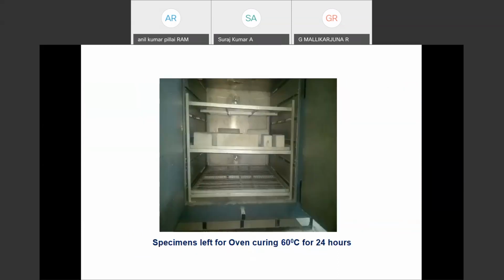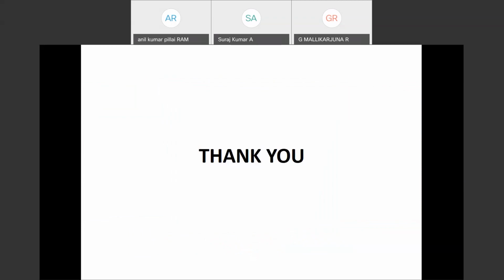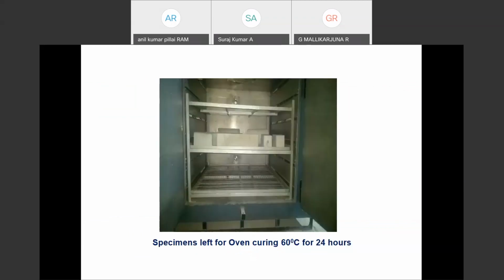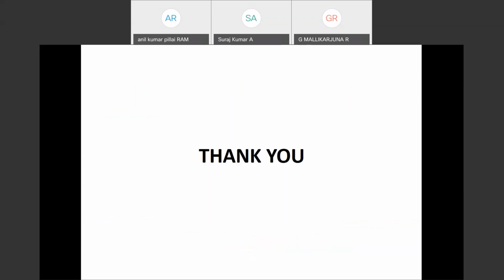And these are the specimens we kept for heat curing at 60 degrees centigrade for 24 hours. And this is about the mix design methodology of geopolymer for the preparation of geopolymer concrete. I hope you got some basic idea regarding geopolymer.